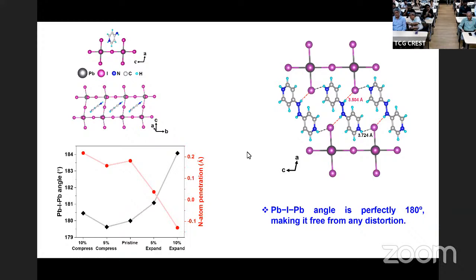And I believe that this actually provides a lot of screening. Because if you create an electron hole there, just by Coulomb interaction, I don't have to have covalent interaction, by Coulomb interaction, if it is close enough, and since Coulomb interaction is long range, that will respond very quickly. And it is the trick of having a benzene ring coming close to where the electron holes are getting generated. That is what, I believe, gives rise to the lowering of the exciton binding energy.